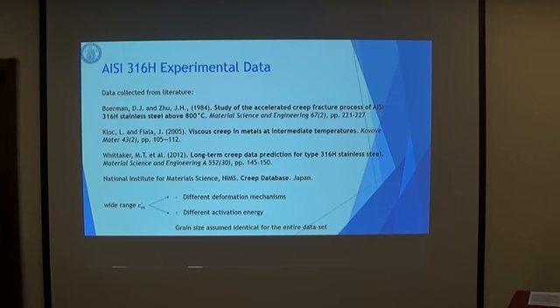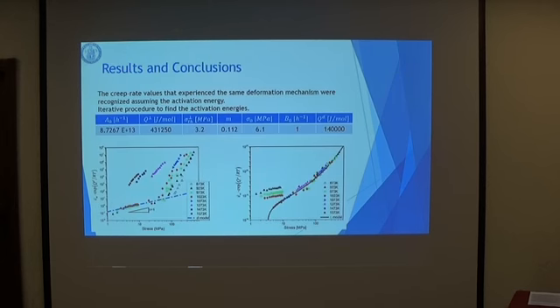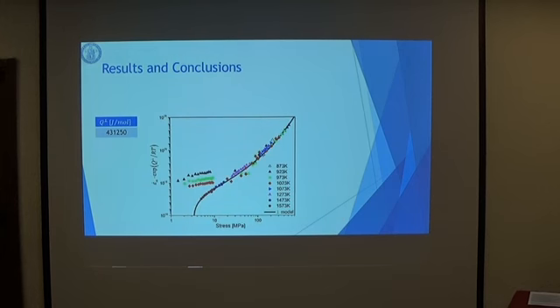In this study, we are not considering a different grain size for the data. So we have normalized the minimum creep rate through the temperature with the activation energy. And the activation energies are consistent with what we were expecting. And here we have, with the black curve, the dislocational contribution of our model and all the data we were collecting.